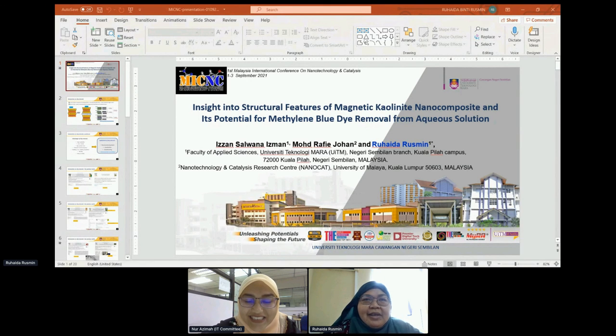Thank you. Yes, I think iron oxide agglomeration is actually a typical problem, because of its high energy and its tendency to agglomerate with each other. But what we can try to minimize it is, perhaps, during the synthesis, where we compare between without and with an inert atmosphere, by including nitrogen gas. Another way, perhaps, is to look into whether we can have more ratios of kaolinite to iron oxide, hoping that the kaolinite can help to reduce the agglomeration of the iron oxides.